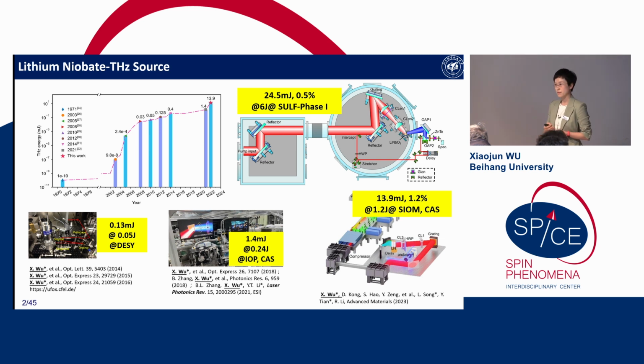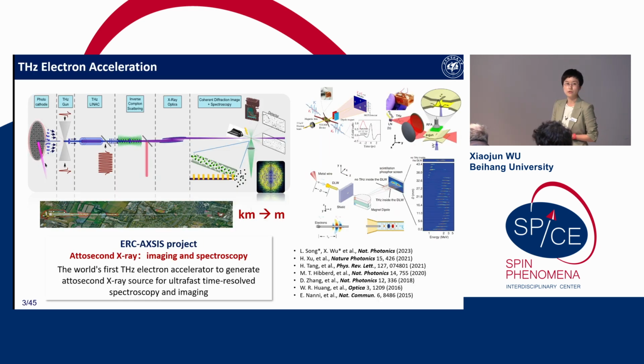This kind of lithium niobate-based terahertz source has a lot of applications. Some people use it for nonlinear terahertz spectroscopy to study spin waves, and so on. What we use this strong field terahertz for is electron acceleration. We use strong field terahertz to interact with electrons to build compact X-ray sources. Recently, we used strong field terahertz to accelerate electrons, and we obtained a mega-electron-volt electron accelerator, but the size is very small.